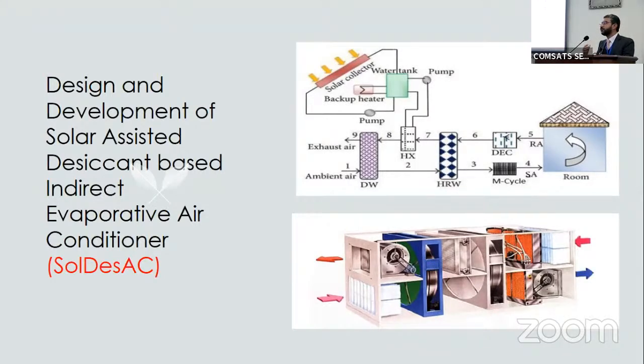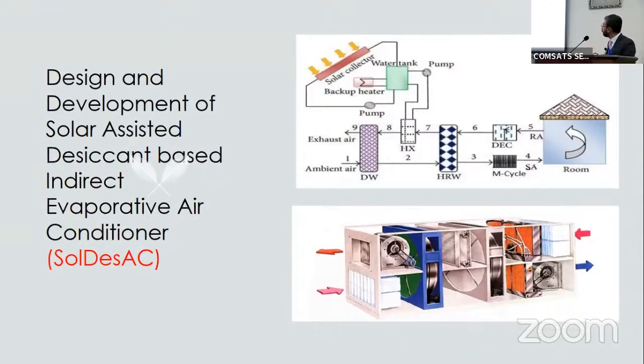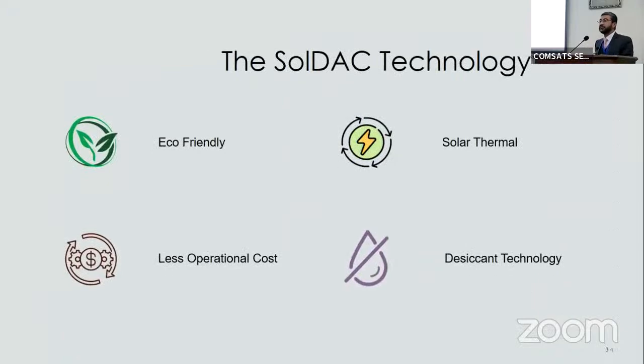But the very important aspect is that when the moisture is absorbed by the silica gel, after attaining its saturation limit, you have to regenerate it. And this regeneration is achieved from the solar thermal system. This is the basic concept: you have to provide hot air to the wheel which has absorbed maximum moisture. For that, we use solar thermal collectors, and these will provide us the hot air which will be used to regenerate these wheels so that they can absorb moisture from the air again.